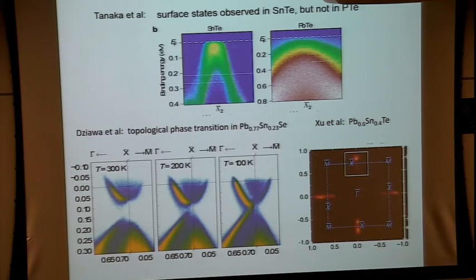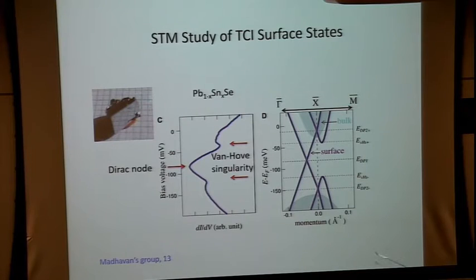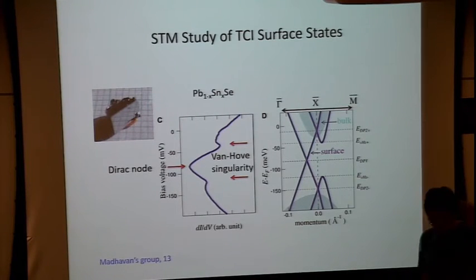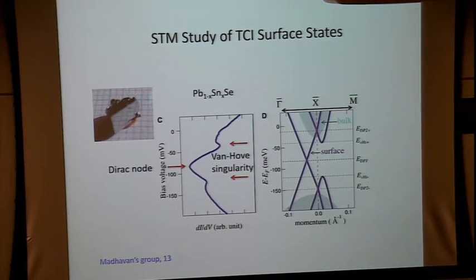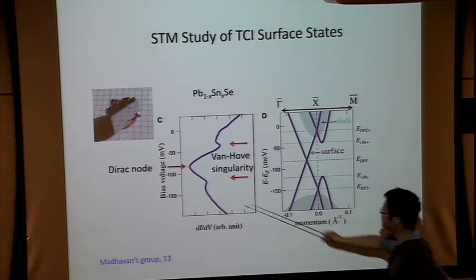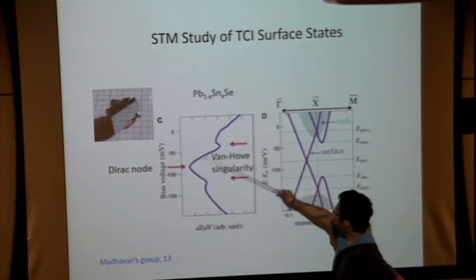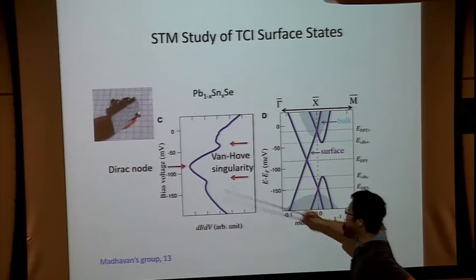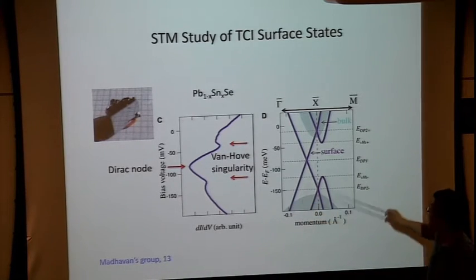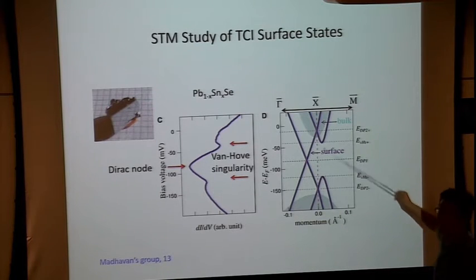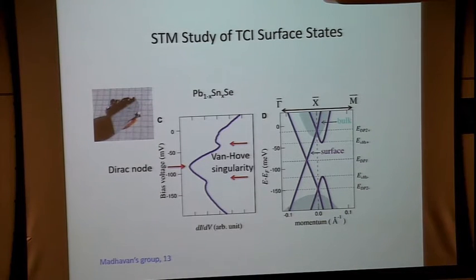Yes. Okay. So let me quickly go through some other interesting experiments before I come back to the theory. From an STM study on lead tin selenide, if you look at the density of states as a function of energy, at low energy there's a Dirac cone, but then there are these shoulders. So these shoulders, low peaks in density of states, are exactly coming from the Van Hove singularity when the Fermi surfaces of the two pockets merge onto each other.